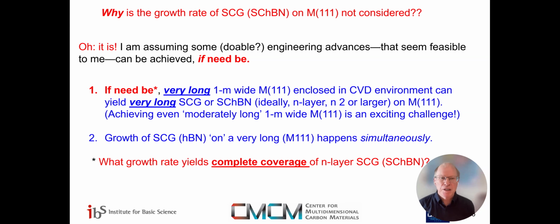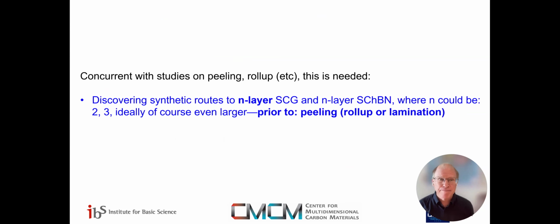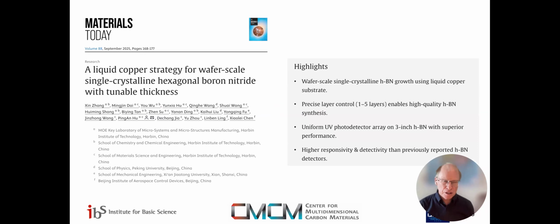So what growth rate yields complete coverage of, for example, N-layer single crystal graphene or single crystal hexagonal boron nitride, and what is the value of N? So we need to find, I think, pretty obviously, monolayer is not going to get us there unless we have a whole lot of factories producing monolayer and laminating. So what we need is we need also synthetic roots to N, where N could be 2 or 3 or even larger. And it's exciting to see in this year, 2025, we've had a few papers appear. Recently, a group at Harbin Institute of Technology used liquid copper and they could grow up to 5-layer in one run.